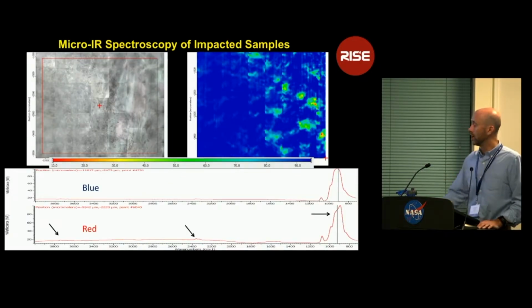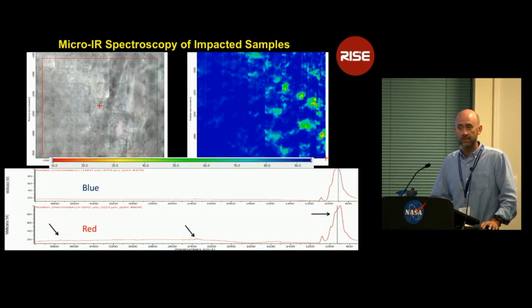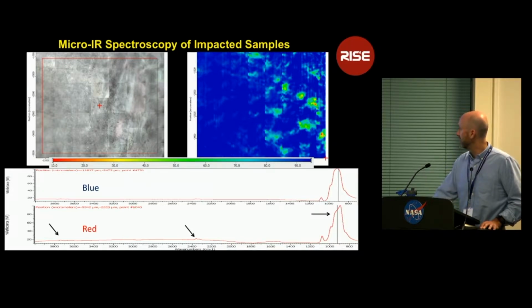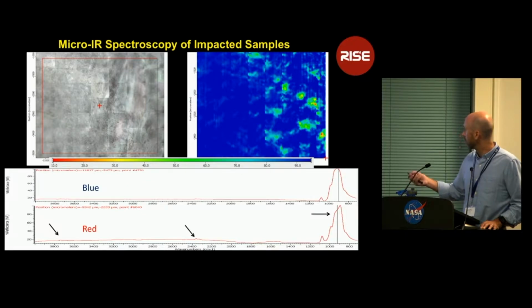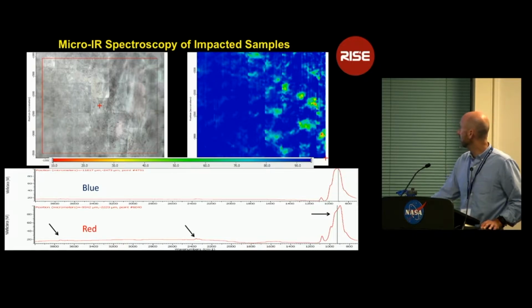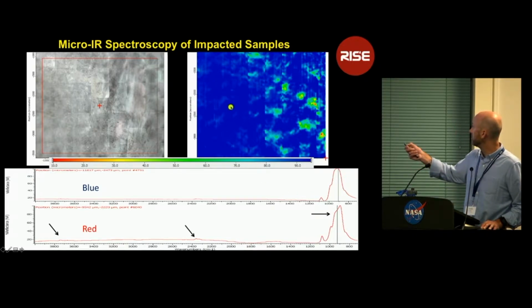Okay, we can do mid-IR spectroscopy at microscopic scales. To do this, we used our IN10MX micro FTIR at Stony Brook. The IR image you're looking at here is an image of the reflectance at this wavelength, which is about 926 wave numbers. What you're seeing here in blue is basically our unaffected pure olivine. This is a beautiful olivine feature right here in the 10 micron region.